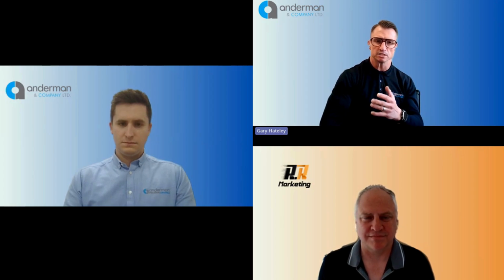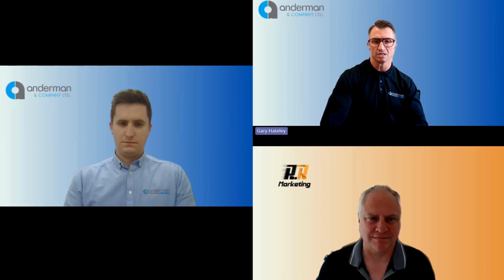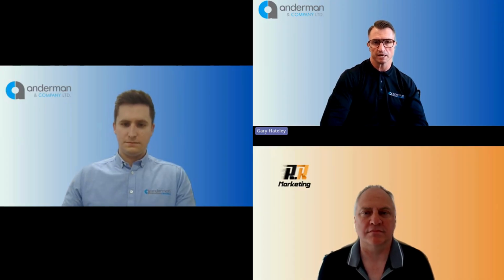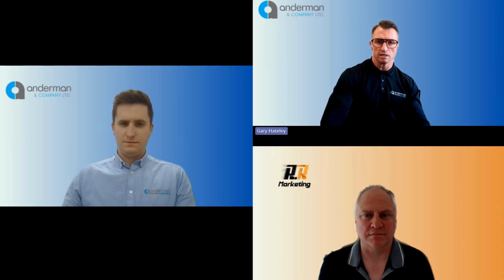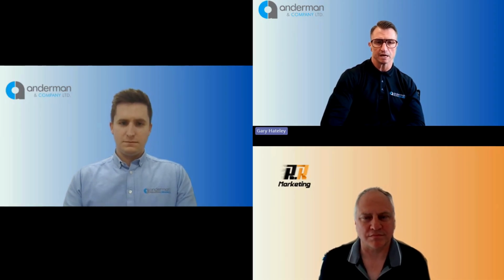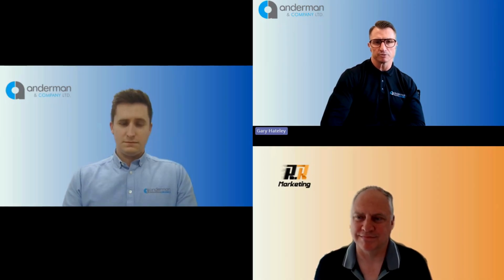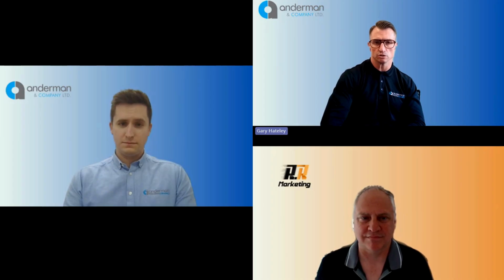This is very much dependent upon thermal expansion coefficient. Generally, lower is better. And thermal conductivity, contrary to that, where higher helps distribute heat better. Materials like silicon carbides tend to perform really well in these kind of atmospheres because they can handle temperature gradients much better than some of its counterparts. The fourth element being oxidization and chemical stability. At high temperatures, reactions with oxygen or other atmospheric elements can degrade materials very quickly.